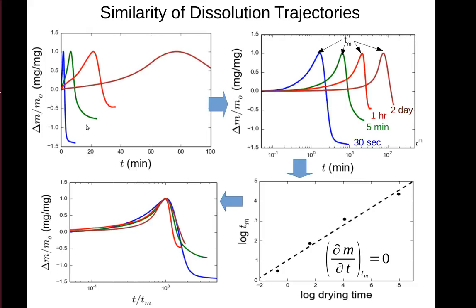Very interestingly, we can collapse these curves down, almost overlapping them onto a master curve. Here we have mass versus time, again from the same plot that we had on the last slide, of 30 seconds, 5 minutes, 1 hour, 2 days. If instead of plotting mass versus time, mass is plotted against the logarithm of time, the curves become very similar in shape and are offset from each other depending on the amount of drying time.